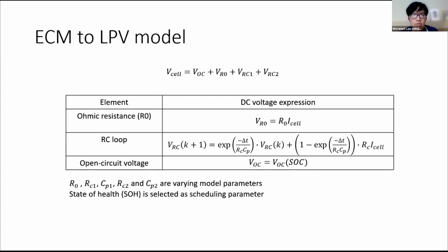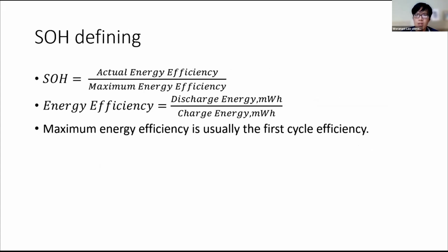To construct the LPV model from the equivalent circuit model, the equivalent circuit model parameters are set to be varying parameters, and the state of health is selected as the scheduling parameter. For this work, state of health for a single battery was defined as the ratio of actual energy efficiency to the maximum energy efficiency. Energy efficiency is the ratio of discharge to charge energy. The maximum energy efficiency is usually the efficiency of the first cycle.